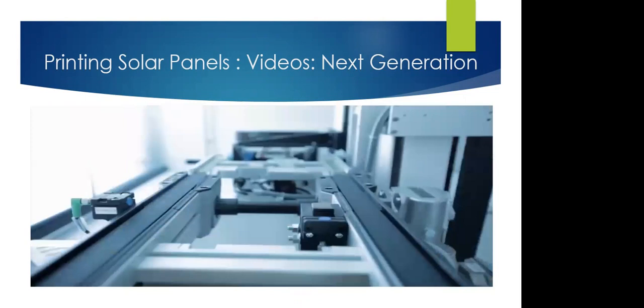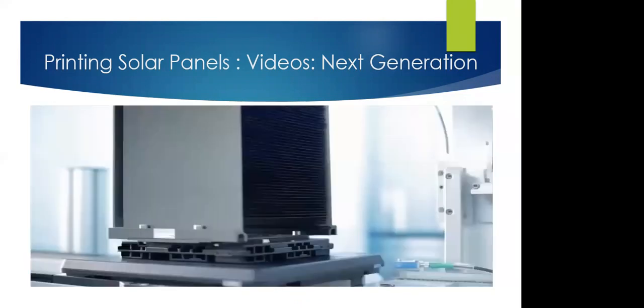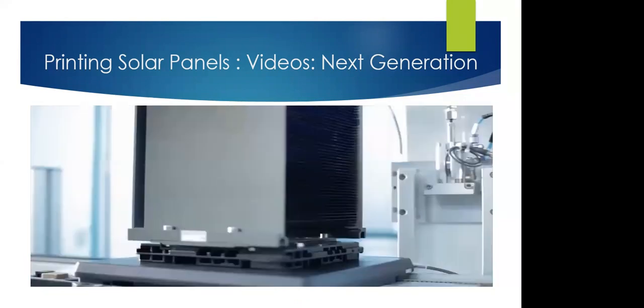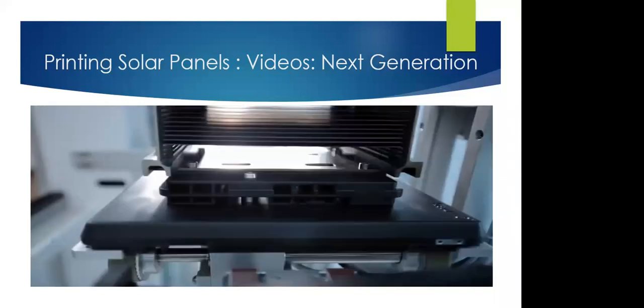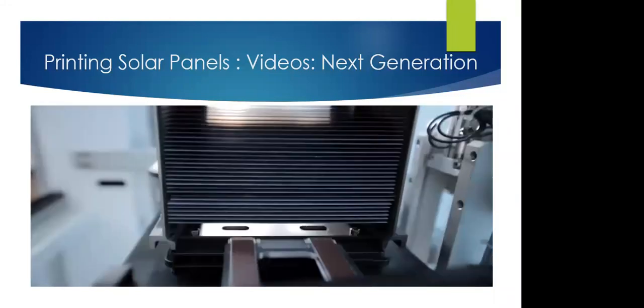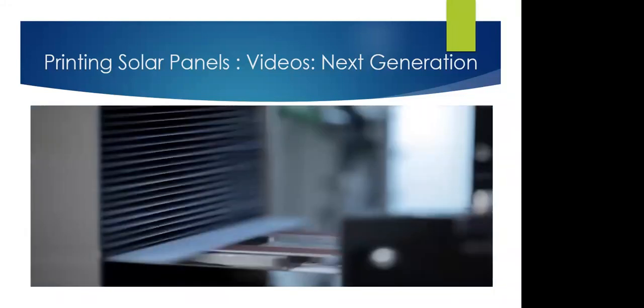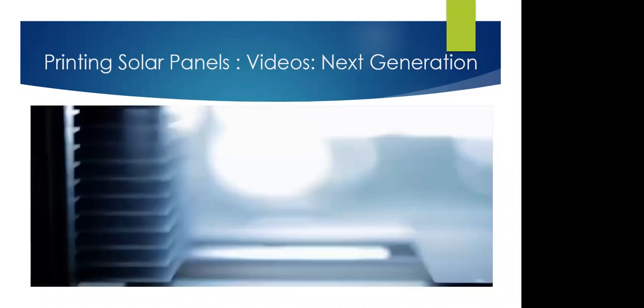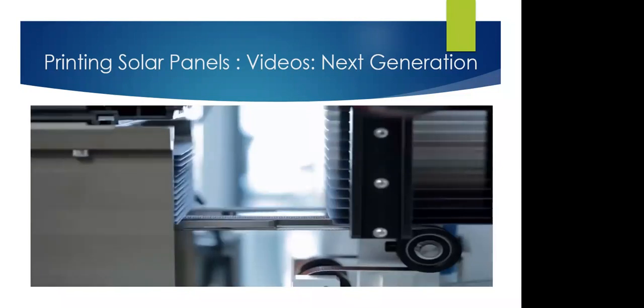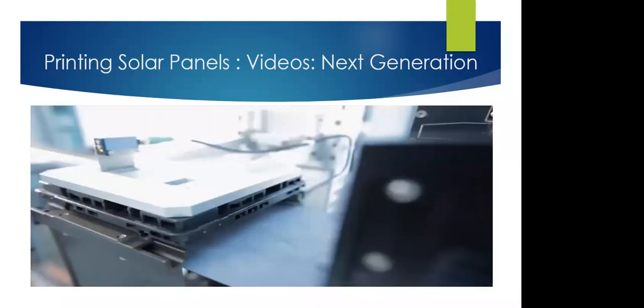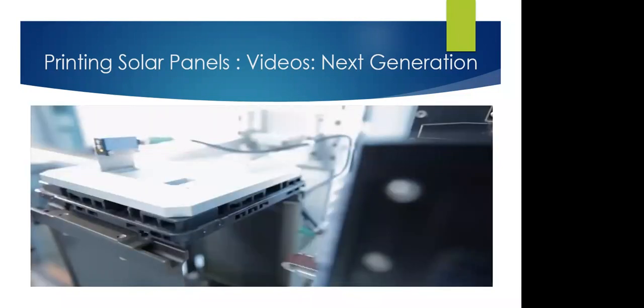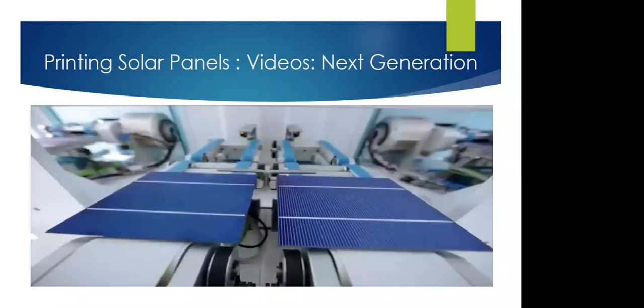The latest version of these converts 22% of the solar power to electrical power. This is more efficient than solar cells made from multicrystalline silicon, but they can't currently be rolled out commercially because they degrade under high humidity and heat. Furthermore, printing layers that are nanometers to micrometers thick uniformly without pinholes over many square meters is exceptionally difficult.